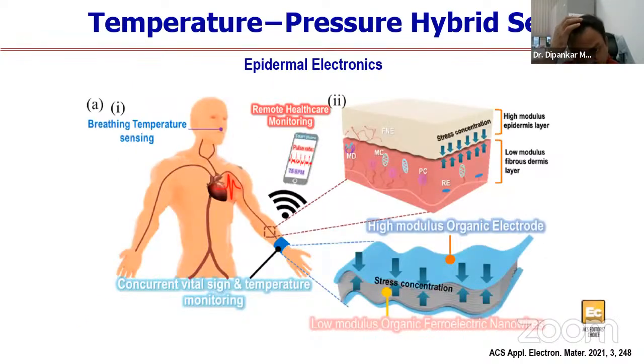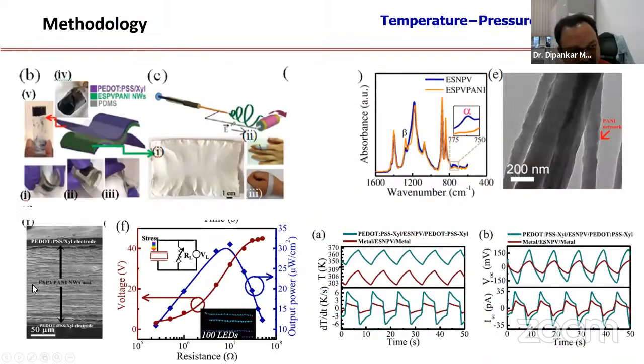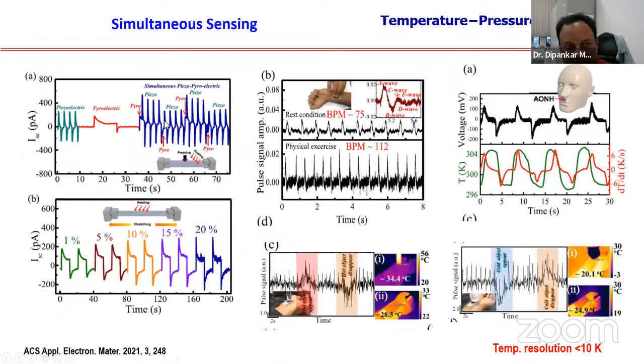Then this is just to make the long story short. As I told, our piezoelectric materials have temperature sensing as well. So we have made electronic skin, but mimicking the skin. What we do is we have two moduli, high modulus and low modulus, as in the skin, and then we make the electrospinning fiber stacking. In reality, they look like this. You see the stacking cross-section image, and then this is the electrode, top and bottom, and then we can see the temperature and pressure variation. So you see the example.